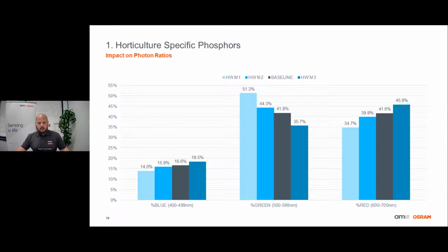Since Horti White is a single phosphor, you can mix two bins to adjust the blue-green ratio in a linear fashion. So you could theoretically mix M2 and M3 together if you needed to get an even closer match of that baseline.